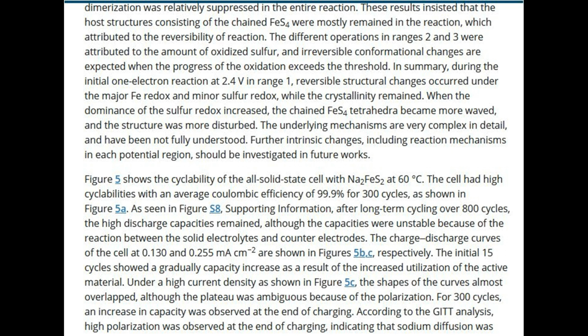Figure 5 shows the cyclability of the all-solid-state cell with Na2FeS2 at 60 degrees C. The cell had high cyclabilities with an average Coulombic efficiency of 99.9% for 300 cycles, as shown in Figure 5a. As seen in Figure S8, supporting information, after long-term cycling over 800 cycles, the high discharge capacities remained, although the capacities were unstable because of the reaction between the solid electrolytes and counter-electrodes.